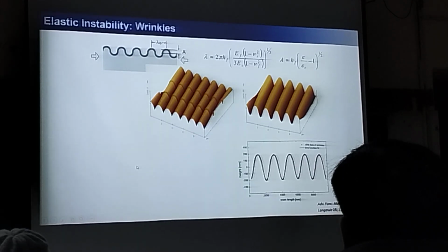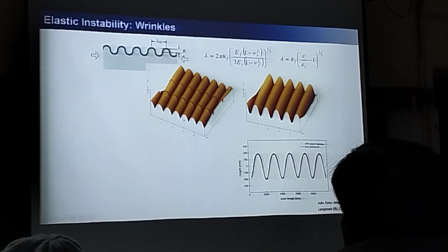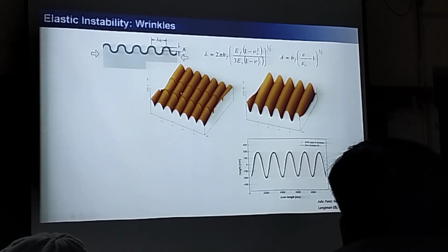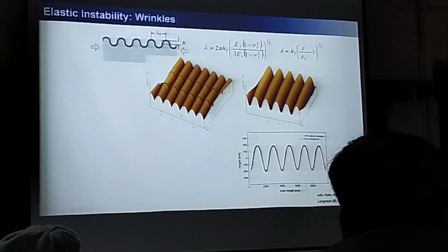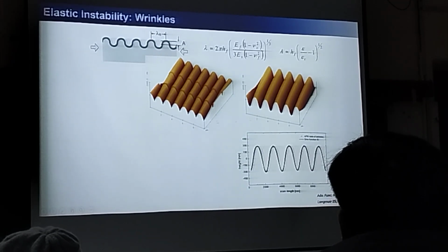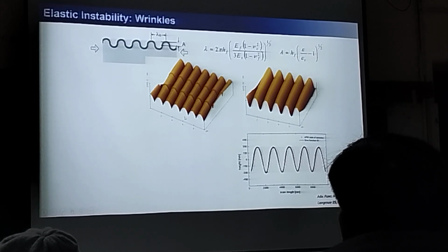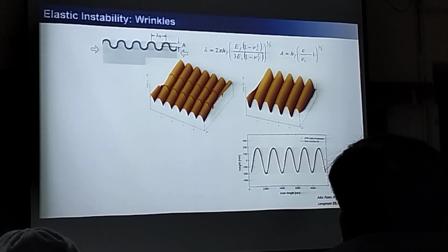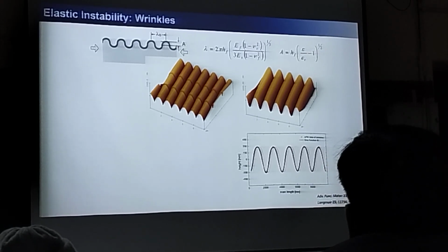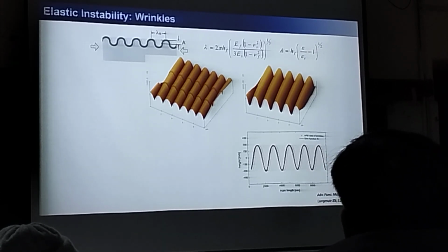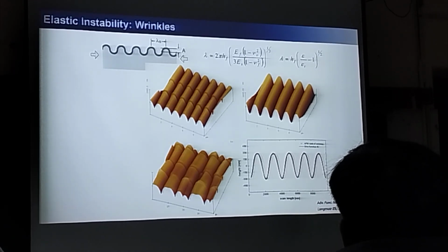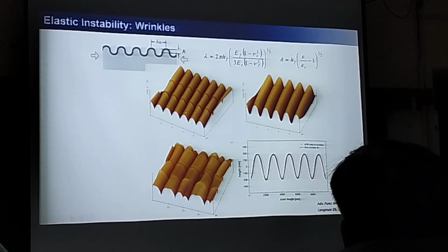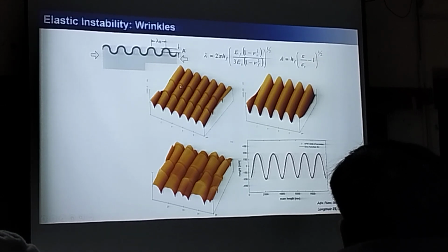So I'll show you. For example, if you go to the extreme parameters, your wrinkles start getting deformed. This is how it looks. The rounding at the bottom, which is there in the sine function, is also lost. So basically, from the elastic instability or the creeping instability, where you have a permanent creeping deformation, the stresses are more concentrated at the very bottom of the polygon. And if you further increase the oxidation time or the strain, you get very deformed wrinkle shapes. So it all depends on your control.